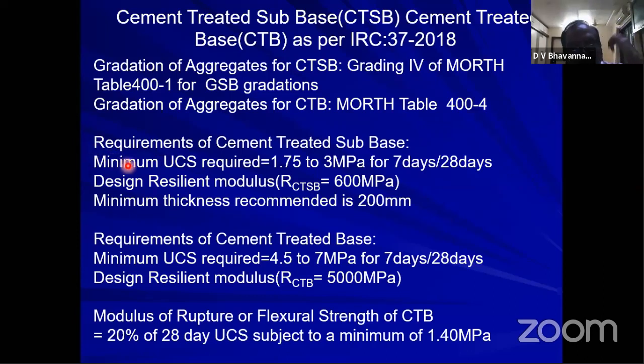What are the requirements of CTSB? Strength requirements: minimum UCS, unconfined compressive strength, required is 1.75 MPa at 7 days and 3 MPa at 28 days. Design resilient modulus is 600 MPa. In the design they are finding resilient modulus for all the layers, including bituminous layers, sub-base layers, etc. The CTSB resilient modulus shall be 600 MPa. If CTSB is provided, the minimum thickness recommended is 200 mm.